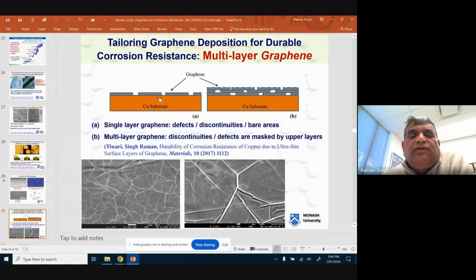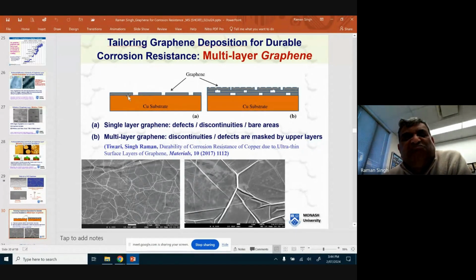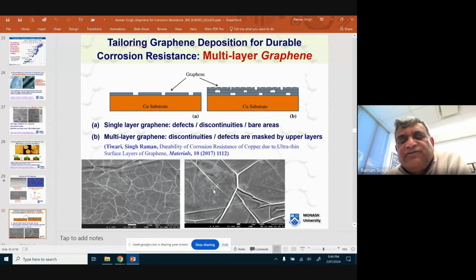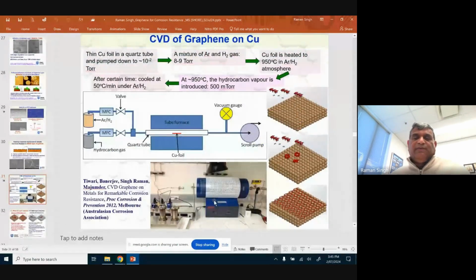So anyway, we came up with a very simple hypothesis. And what was that? That it is not possible to develop single layer graphene with continuity. Why don't we develop multi-layer graphene? So this is what we did, that we have single layer, it has discontinuity. If we have multi-layer, it is most likely that this discontinuity will be masked by upper layers. That was a simple hypothesis we started to work with, and we developed graphene, and we could show that yes, you have wrinkles in the layer, but wrinkles of the lower layer is masked by upper layer, which may itself have wrinkles. So that was the hypothesis.